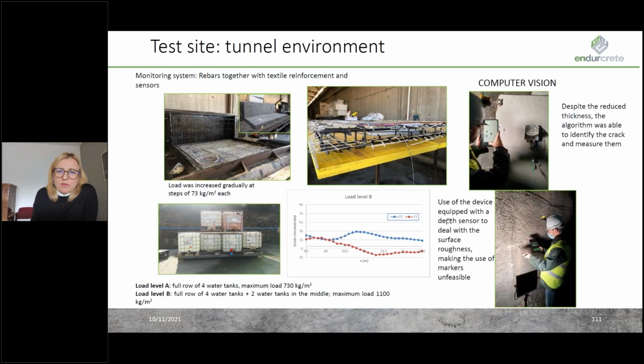We can see here the preparation of the samples. The preparation included the usage of the textile reinforcement and fiber optic sensors. This is the two-stage loading before placing the panels in the tunnel. As well, initialized cracks were performed in order to test the computer vision technique for detection of the crack location and the width. And as well, the device for measuring the surface roughness was applied.